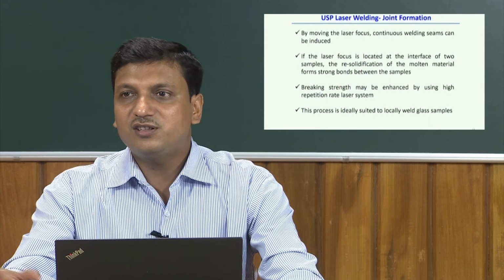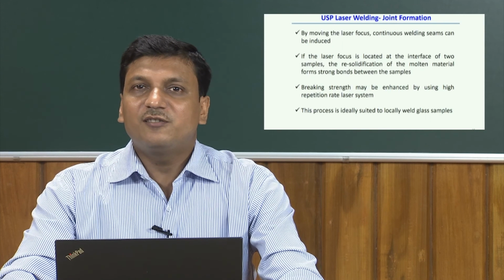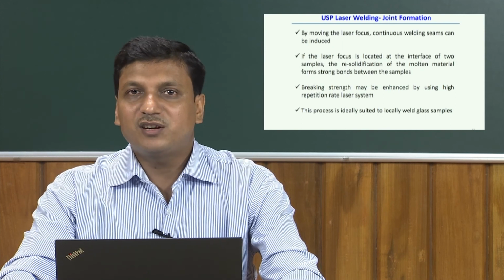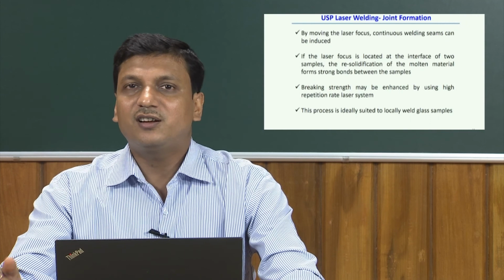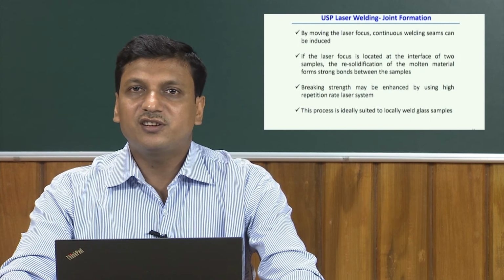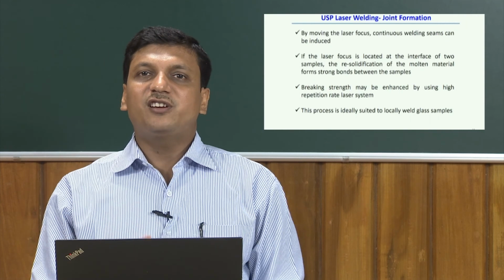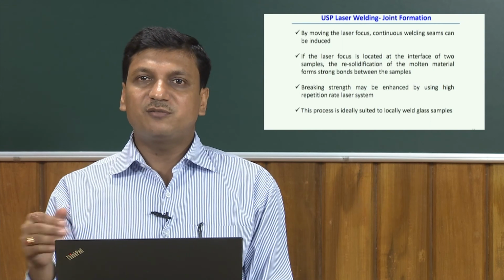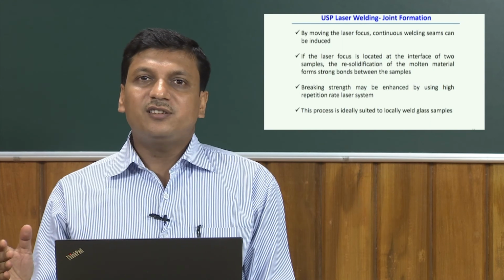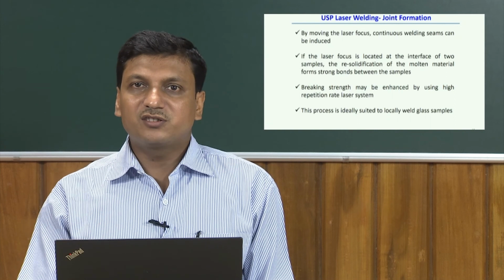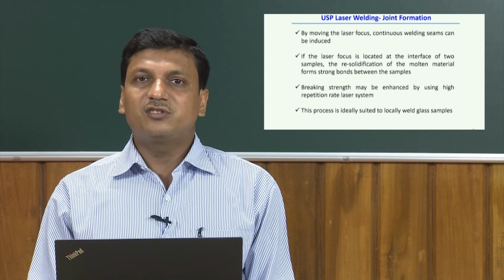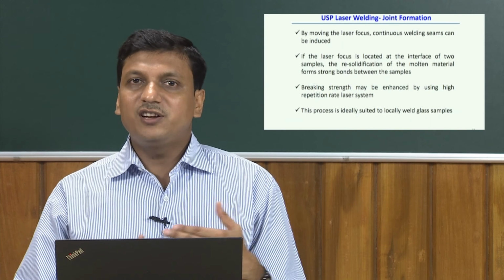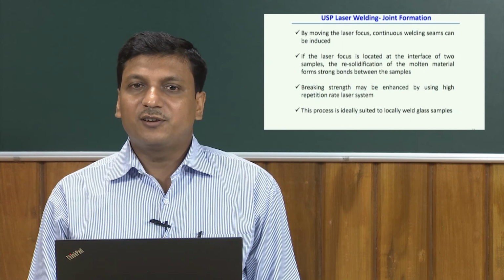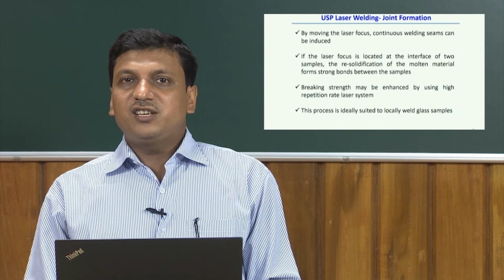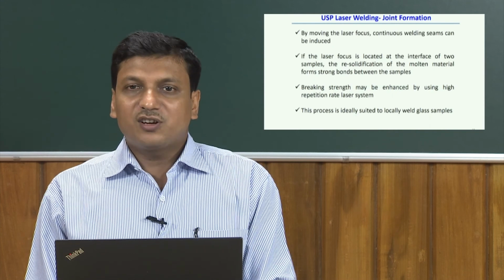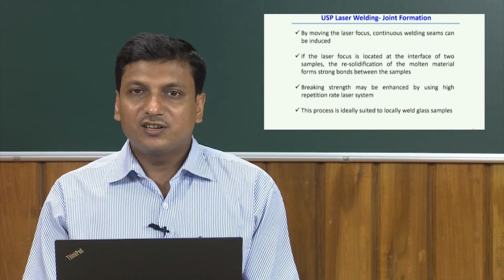In general, a very low repetition rate in the case of an ultrashort pulse laser, and at the same time a high pulse energy, is more suitable for the material ablation process. So, it simply vaporizes the metal very quickly. But on the other hand, a high repetition rate with low pulse energy is mainly suitable for the joining or welding mode of the material. Therefore, this is more suited for the joining of glass using the ultrashort pulse laser,